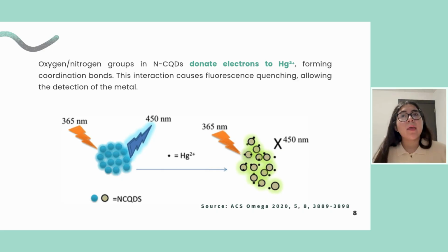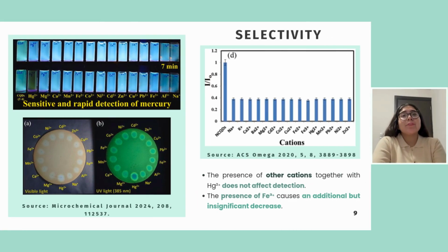These functional groups exhibit a strong affinity for mercury ions and form coordination bonds through electron pair donation, leading to fluorescence quenching. On the other hand, Risby and co-workers characterized their synthesized carbon quantum dots using techniques such as Fourier transform infrared spectroscopy, ultraviolet-visible spectroscopy, and transmission electron microscopy. Their findings indicate that positively charged mercury-2 ions interact with negatively charged carboxylic groups on the carbon quantum dot surface. These interactions result in the formation of unstable carbon-mercury complexes, which subsequently convert into mercury-oxygen compounds, ultimately causing fluorescence quenching.